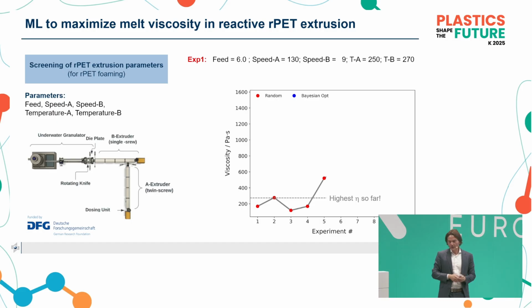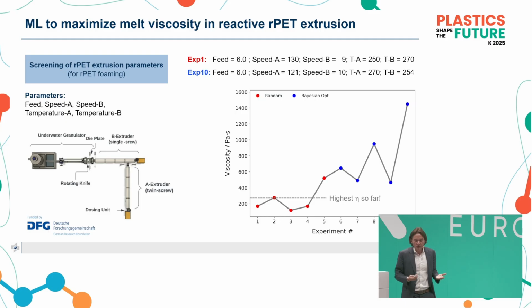The first 5 dots, these reddish dots, are the random experiments. And you already see the average, the highest so far, was relatively low, and we wanted to increase the viscosity. So let's see what happened with Bayesian optimization. 5 more trials, and we've been tripling the viscosity we gained so far. So that's the value, from my point of view, the value of small data. You can start small in order to, for instance, optimize your processes or optimize your formulations.